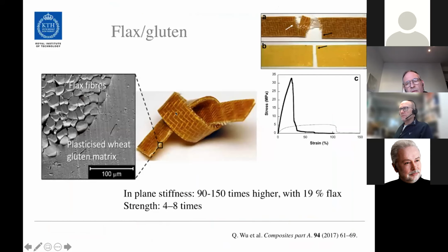If you want to improve the strength: when you put the plasticizer in the material, the strength is reduced. That you can compensate for by putting fibers into the material. This is an example of a non-woven flax fiber network, which has been combined with the gluten. And that gives you very high strength and also flexibility, as you see in the middle figure here.